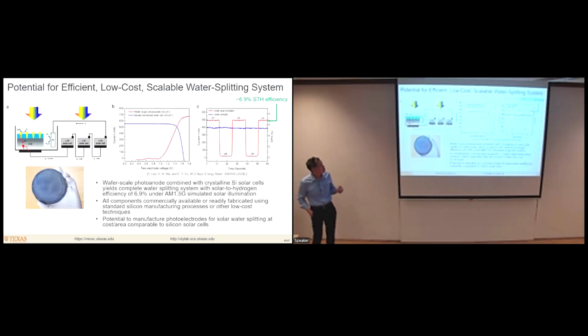And then to try to get a solar to hydrogen efficiency out of this, what we did was we took one of these wafer scale photoanodes and we combined it with just off the shelf silicon solar cells, so that we could get the full reaction occurring and extract a solar to hydrogen efficiency. We get around 6.9%. To give you some calibration for that number, one of the standard benchmarks for the US Department of Energy for solar to hydrogen efficiency that would be required to have cost-effective green hydrogen production using this kind of approach is about 10%. If the performance of the wafer scale photoanode were as good as the small area photoanodes that we made, which is certainly something that can be achieved with probably just moderate effort, and that's something we're working on now, this efficiency would be roughly 12 to 13%, which is really good.